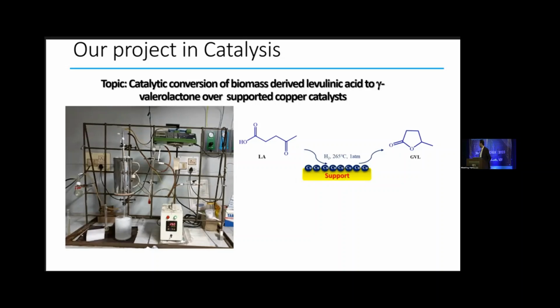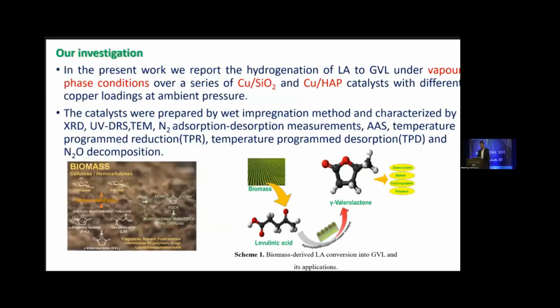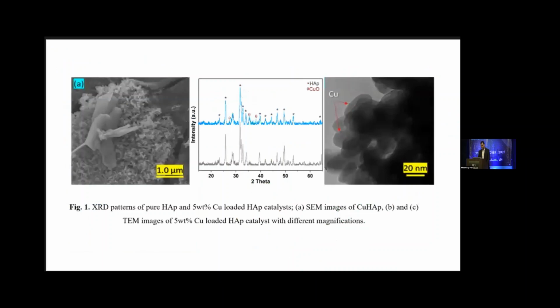At the beginning, we are purging hydrogen for 1 hour to activate the catalyst at 300 degrees Celsius. So we explore different supports like mesoporous silica and hydroxyapatite, using copper as a catalyst. And we also characterize their morphology using TEM, XRD, TPR, and TPD.